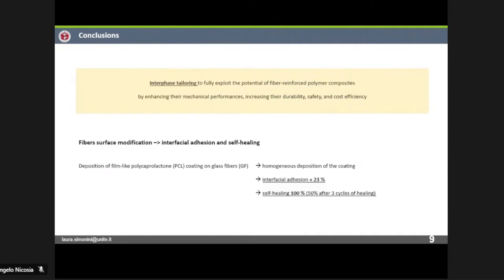So in conclusion, we were able to tailor the properties of the interface between epoxy matrix and glass fibers by fiber surface modification to increase interfacial adhesion and to provide self-healing capabilities. We did this by the deposition of a polycaprolactone coating on glass fibers. We obtained a homogeneous coating, an increase of 23% of the initial adhesion, and a fully repairable interface at the first cycle, 50% at the next cycles.